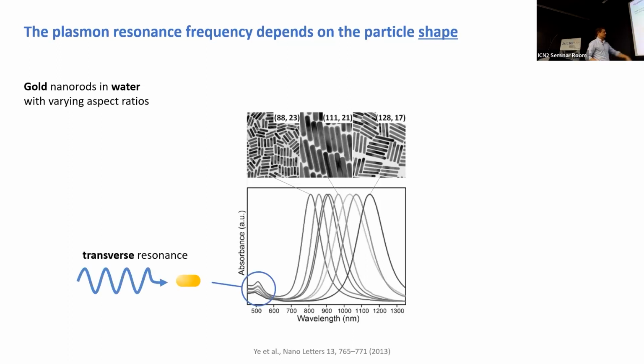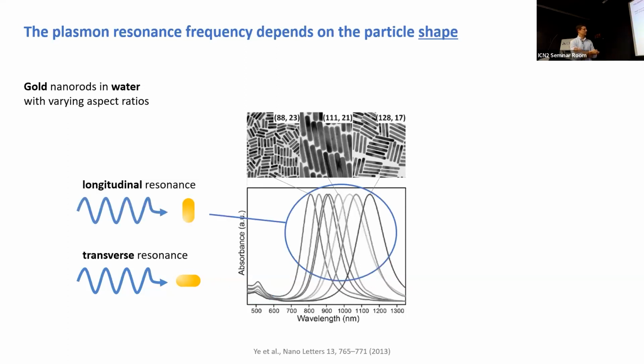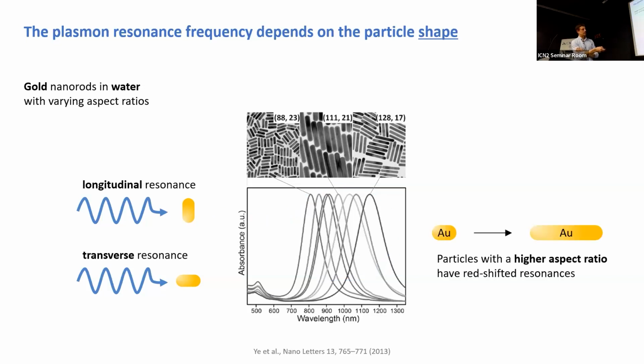Actually, there is a couple of resonances here because you also have two typical dimensions in a rod. You have the width and the length of the nanorods, so you can see both contributions here. But in general, particles with a higher aspect ratio also have redshifted resonances. Now, plasmon resonance frequency depends also on the particle composition.